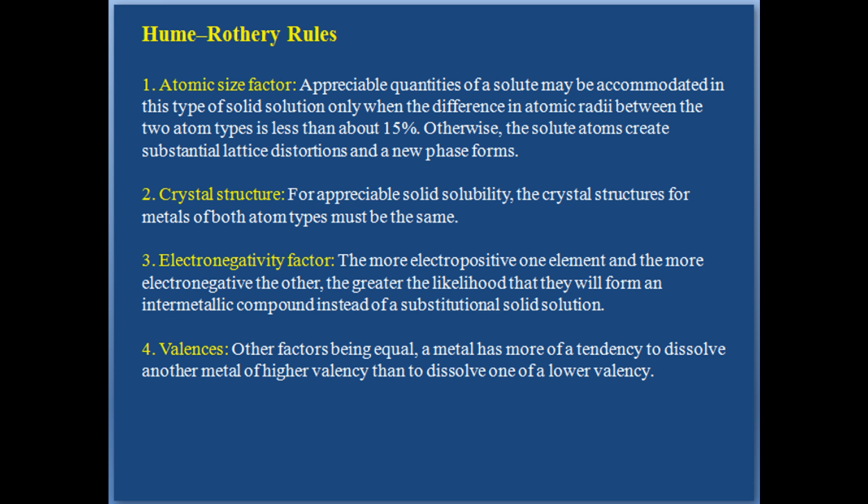This is the third Hume-Rothery rule. Fourth is valences. Other factors being equal, a metal has more of a tendency to dissolve another metal of higher valency than to dissolve one of a lower valency. We have discussed these four Hume-Rothery rules.